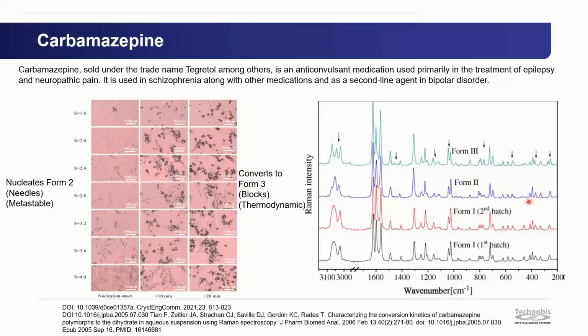And then finally, a case of carbamazepine, which has both optical and Raman spectral changes. Carbamazepine is used in a lot of research and is an anticonvulsant medication used in treatment of epilepsy. It has several forms, but 2 which have very different morphologies: form 2, which is metastable in needles, which in pharma are quite difficult to handle and unwanted. And form 3 is the thermodynamic form and has these block-like crystals. So you can observe the physical change in morphology, but you can also observe the Raman spectral change going from form 2 to form 3 by several peaks.